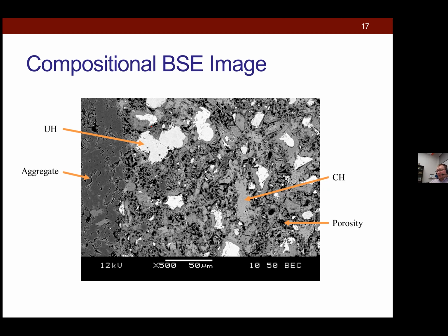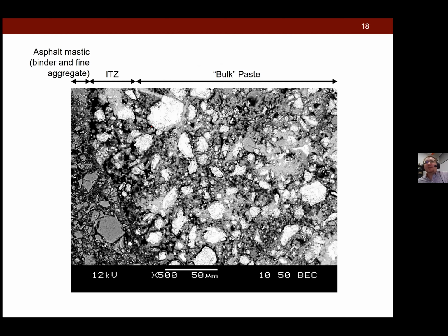Okay. Now, this in and of itself caused some problems because some of the epoxies that we would typically use actually acted as a solvent for the asphalt. So that meant we had some issues with epoxy impregnation, but we eventually were able to successfully epoxy impregnate the sample and develop some nice micrographs like this one.